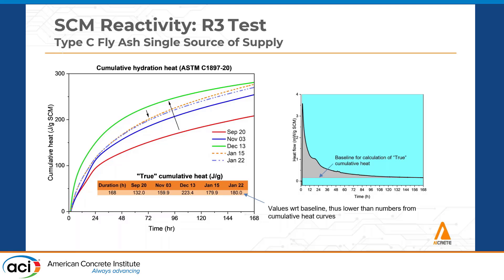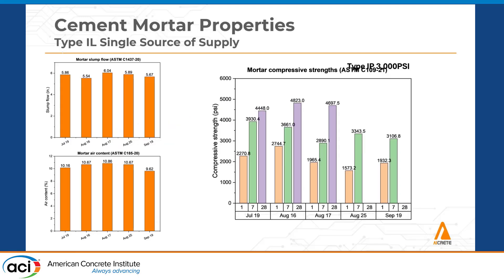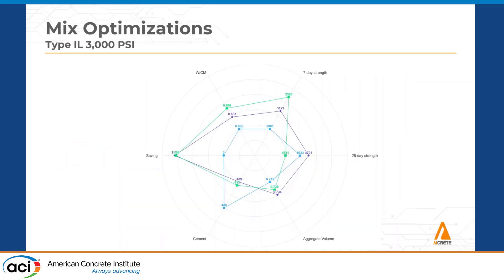We've had a lot of these things come up — as Jason mentioned with complaints on the contractor side if they don't know what's coming, unfortunately the same thing can go for the ready mix supplier as well. Back to IL: this one shows mortar compressive strengths, slump, and air content. You can see the dip in strengths with the variation — the August dates were the ones that had more of a Type IL performance.